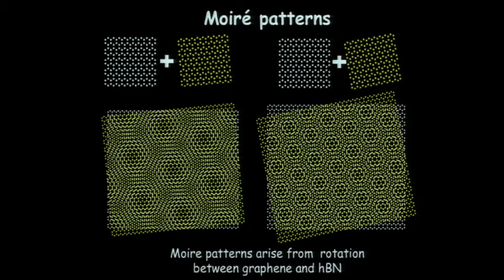So we have here the boron nitride. We put the graphene on top of it. You put it on top with a 5-degree twist angle, and you see this Moiré pattern here, here, here. If you go and put it with a 10-degree twist angle instead, then you see a pattern here where the Moiré pattern gets shorter. So just by controlling the twist angle between them, you can get different Moiré patterns.